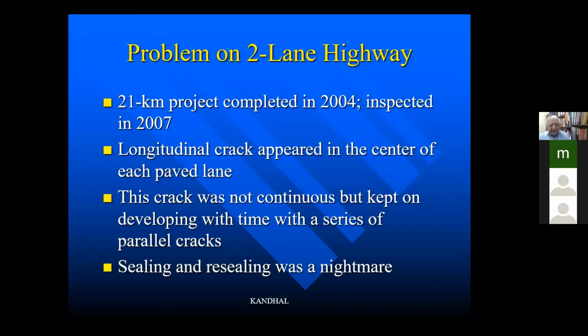You don't get any crack between the lanes. When you pave a lane, you can have a construction joint problem between the 2 lanes, but you don't get a crack right in the center of the paved lane, in the center of the wheel path. This crack was not continuous, but kept on developing with time as a series of parallel cracks. Sealing and resealing was a nightmare. They got fed up in 3 years.